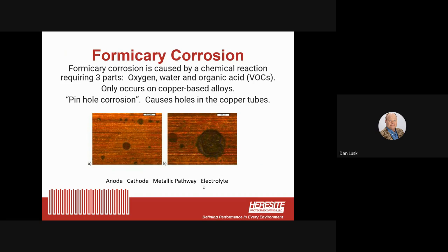We also deal with formicary corrosion. This is a corrosion that happens with copper. Oxygen, water, and organic acids combine and create what's also called pinhole corrosion. So if you have a copper tube that has a hole in it, it has a leak in it, it's usually due to formicary corrosion.